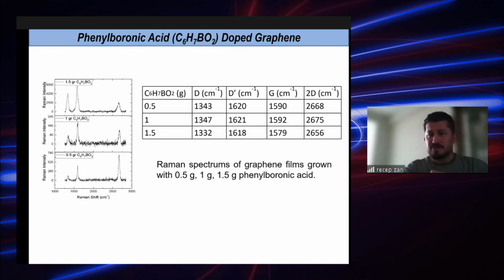And the last study was phenylboronic acid. Again, this is used as both carbon and boron source. We didn't feed our CVD system with any other gases. So we tried to adjust the growth process using 0.5 gram, 1 gram, and 1.5 gram. As I mentioned, this was in a solid form. And thanks to the 3-zone CVD system, we were able to use different zones with different temperatures to grow graphene using these kinds of materials in different zones.